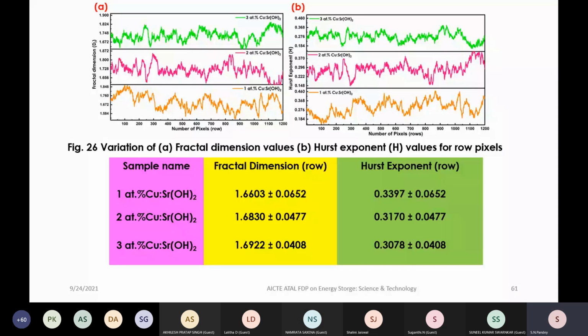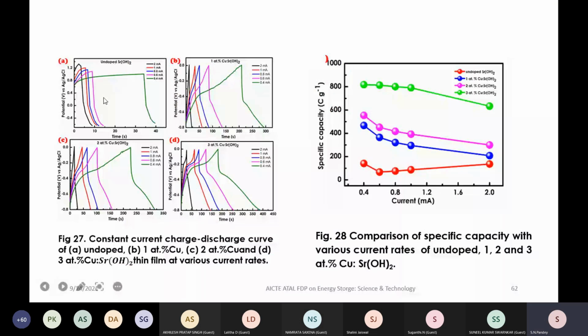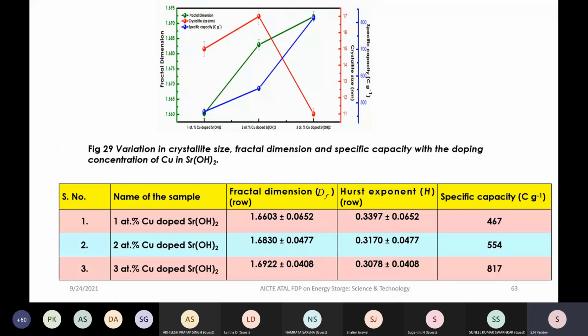One can see that it has the maximum value for the 3 atomic percent. So let us check it here. This is the charge discharge and comparison of the specific capacity at various current rates, the experimental side. If you compare the fractal dimension, Hurst exponent and specific capacity, the 3 atomic percent copper doped strontium hydroxide has the highest fractal dimension, and the specific capacity is also the highest among all three.